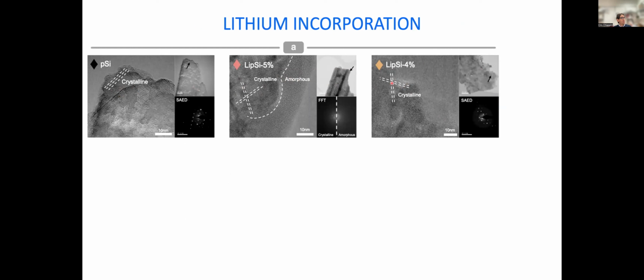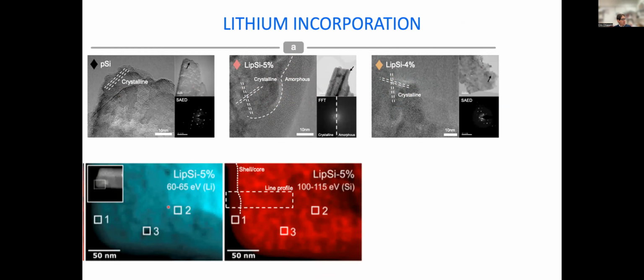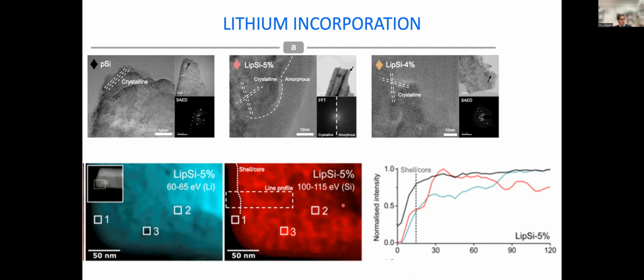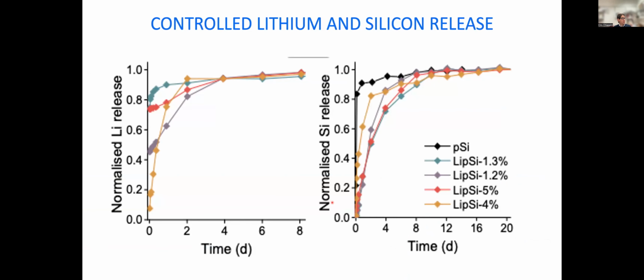And we can see that we can incorporate lithium in different ways. We can either maintain the crystalline structure of the silicon all the way to the edge, and the lithium inserts within the crystalline structure, or we can create an amorphous layer on top of the original porous silicon. And regardless of whether we have only a core or a core-shell structure, we can see that lithium is present throughout both the core and the shell of the material if we look at it by EELS. Okay, and this is just the relative distribution of the silicon and of the lithium within the two core and shell structures.